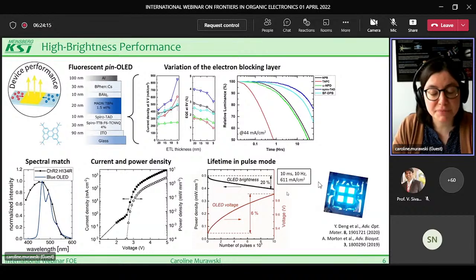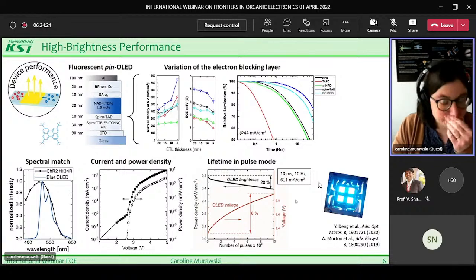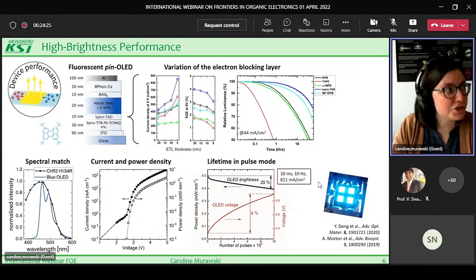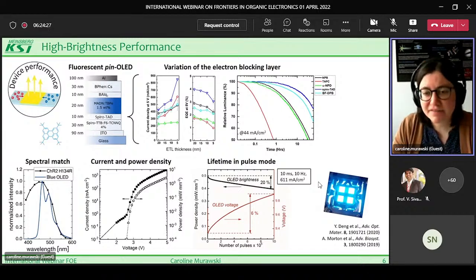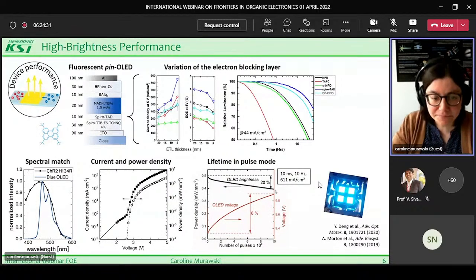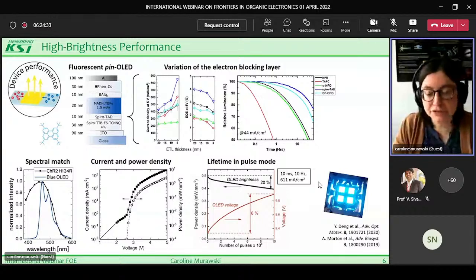And this is much, much higher than what you have in displays. If we convert this to candelas per square meter, I believe we are in the range of maybe 60,000 candelas per square meter or so for blue OLED. So this is much brighter than what you would use for displays. For displays, we are more in the range of microwatt per square millimeter.